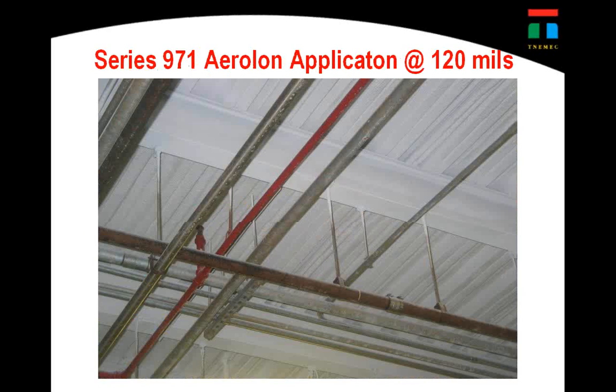What we did, we calculated the amount of dew point, temperature, and humidity, and came up with a design thickness that would eliminate or greatly reduce the potential of condensation from forming in this location. So we're applying the coating directly to the steel substrates in all of these locations. And unlike a conventional insulation, whether it be foam or mineral wool or some other form of insulation, you have it directly applied to the substrate.